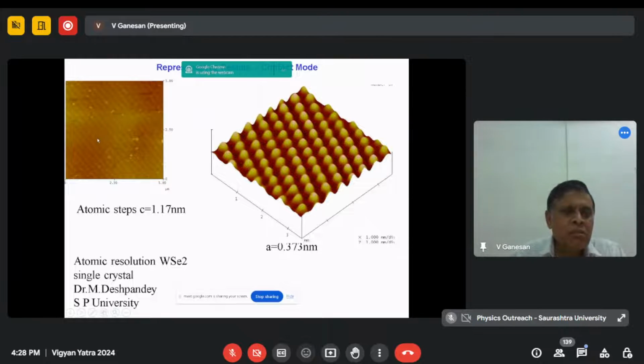And if you see the steps of each of them, what is the vertical dimension from one step to another step in the Z direction? You can see it is about 1.17 nanometer on average. Okay, that's equal to 11.7 Angstrom. 11.7 Angstrom is the c lattice parameter of this particular tungsten diselenide. That's all.